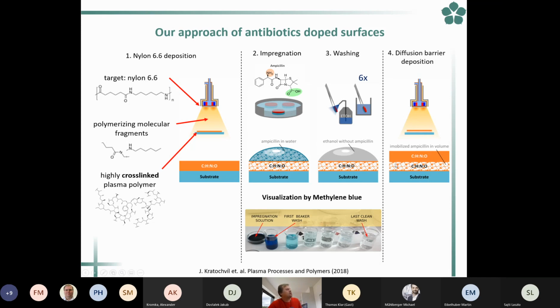Once the ampicillin was stored inside, because of the natural amine grafts, we were able to coat it once again as some barrier layer, which allowed us to control the release of the antibiotics. This work is partially inspired by the coatings, for example, of some implants, where the antibiotics are stored exactly on the surface, or let's say in the surface, in the buffer of thin films, and then can be released with the defined time and with the defined amount.